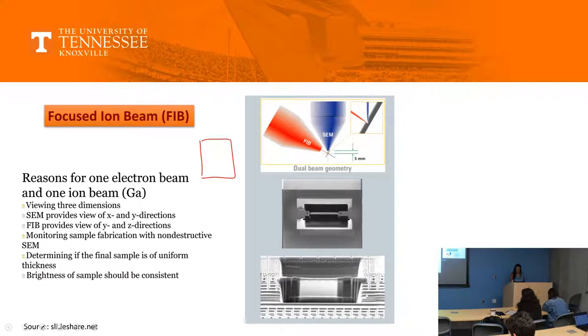You have your sample like this, right? It's a full sample like this. And what do you do? When you do any mechanical polishing, you are damaging this entire sample, isn't it? I would have to put the sample on a polishing machine, right? And then slowly this entire sample would be grinded into a small thin thing. You do any polishing, you're simply grinding it. So what did you lose? Your entire sample. What can you do now? Nothing, right? That's the top reason why people started using FIB, a non-destructive technique.